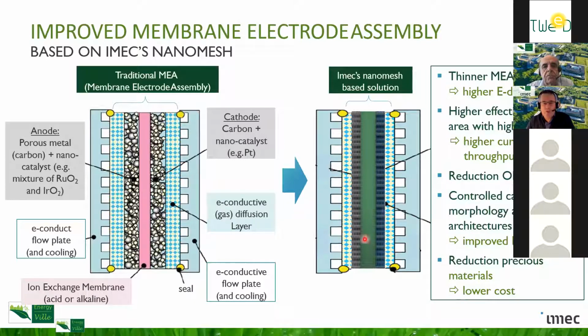By using a nanomesh structure here, which I will explain, you get a higher effective surface. With this bigger surface, with high porosity, you can actually have a high throughput. There is an intense contact between the different elements, which gives you a reduction of the ohmic losses. And by using nano materials, with specific nano materials for the catalyst, we can have improved kinetics. And then we also reduce the number of precious materials used. In principle, there are no precious materials used. And we can lower the cost of the whole system. So this is what we're working towards.